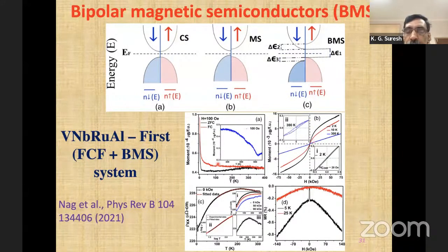But if you combine experimental and theoretical data, you will be able to show exactly what happened to the system. Magnetism-wise, it's a fully compensated ferrimagnet. It has an extremely small moment, again 10 to the power of -4 Bohr magnetons, and it has a bipolar magnetic semiconducting state. The band structure is something like this. This is something very new, as you can see, 2021.